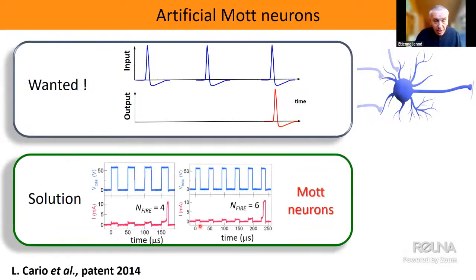And look at what we have done. So we have tried to do the same. In this example, we have sent 4 pulses or 6 pulses in a burst mode. And you see that nothing happened during the first 3, or during the first 5 pulses, but on pulse number 4 or on pulse number 6, we have the insulator to metal transition that appears, creation of the conducting filament, giving rise to a burst of current flowing through the sample.